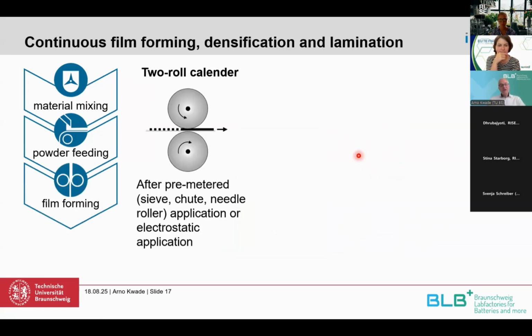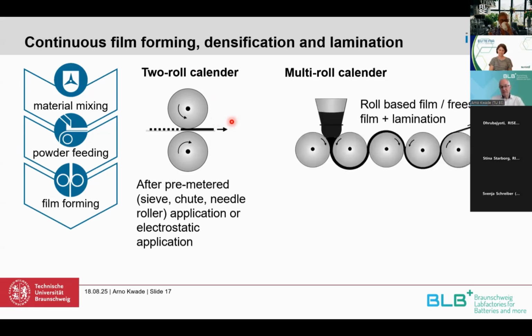This calendering machine is really necessary, independent of the dosing method, to stabilize and form the layer. It can be a simple 2-roll calender if you have a special dosing system, but usually it's a multi-roll calendering machine where you form the film and then decrease the thickness of the film, and then you have the lamination here at the end on the substrate.